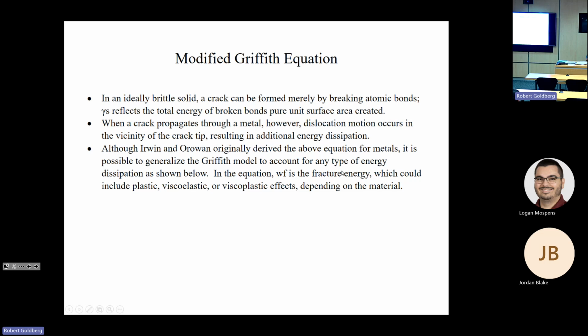So Irwin originally derived that equation that we just wrote down for metals, but it's also possible to generalize the equation for any type of energy dissipation. So what we do is we just say that our fracture stress is equal to 2 times the modulus times this new term W sub F divided by pi and the half crack length, all to the 1/2 power. So this W sub F term is going to be our new generic term to account for the fracture energy due to whatever. It's the energy due to the breaking of atomic bonds. It's the energy due to plasticity effects. It's the energy due to viscoplasticity effects, which we're not going to talk about much, if any, here, but it's just a generic energy to account.